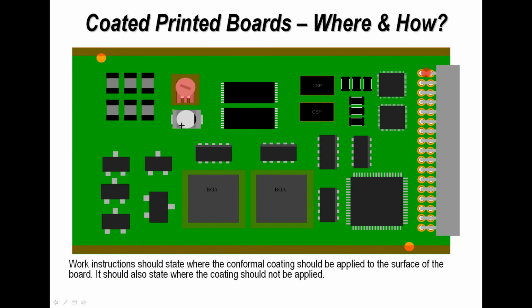Now, a key thing is that we may be using this as voltage in, voltage out, so it may be very important to make sure the terminations are protected by conformal coating. But it's an issue, and has been for some time, to also make sure the body contact, or the contact between the pins and the plastic, doesn't allow capillary action and allow the solvent or the conformal coating to penetrate up through the connector interface.